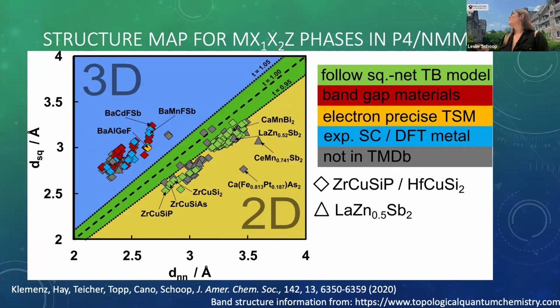Whenever I color them red, they have a wide band gap. So no Dirac crossings. But most interesting are the ones that are colored blue, because those ones in PBE DFT in the databases, they're often metals, sometimes they're topological semimetals. But you might have heard before that DFT, if you use simple functionals, tends to underestimate band gaps. So you want to be careful. So what we did is we typed this chemical formula into Google together with the word band gap for each of these blue materials. We found experimentally measured band gaps in all these materials.